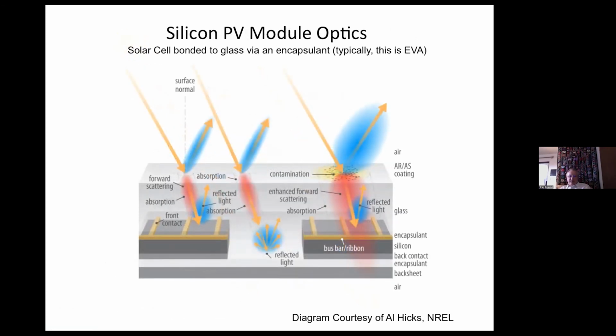Now building this up, you see each slide that I've shown you is building this up from simple to what the reality of the situation is for soiling. Again, here's clean on the left side and contaminated or soiling on the right side. When you have a photovoltaic module, you have the solar cell bonded to the glass by an encapsulant, which usually matches somewhat closely to the index of refraction of the glass. So there it becomes one optical block. But again, in between, you have some reflected light, which bounces around and is collected by the solar cell.